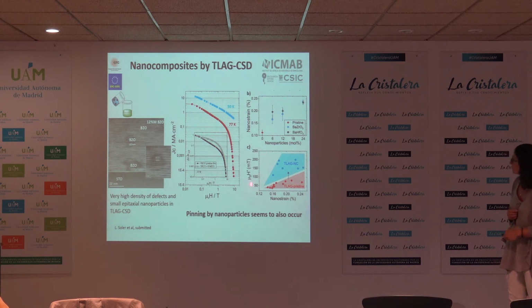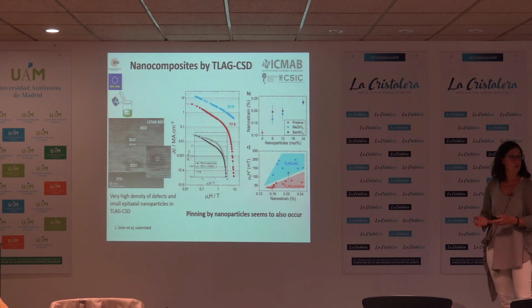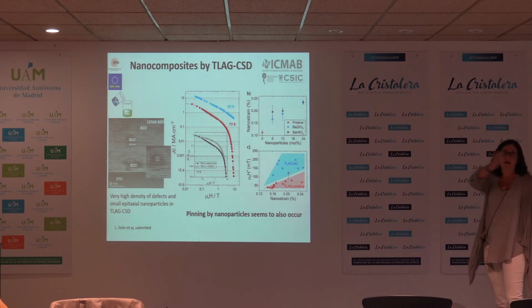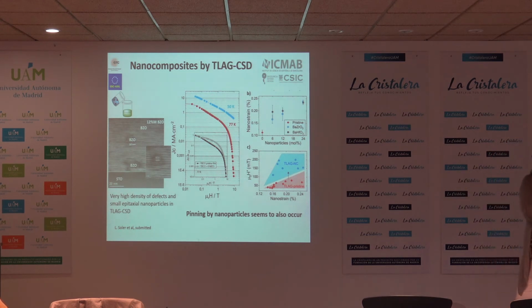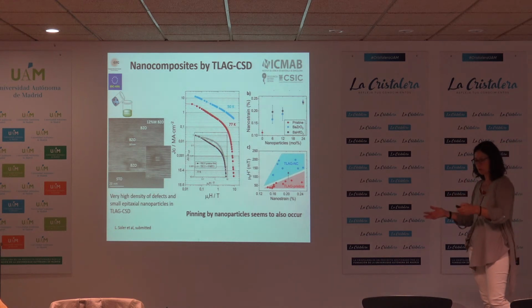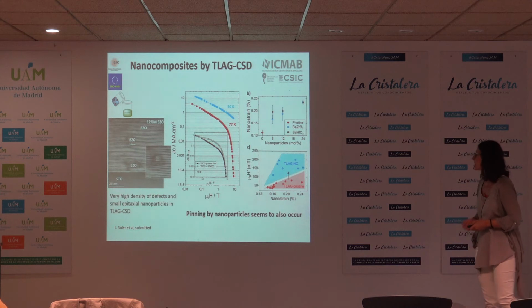And we also have been able to see that the H star depends on the nanostrain, but also for the same nanostrain, we do have higher H stars. That means that the small nanoparticles are also contributing to this process, so that we can really get all the knowledge and all the benefits that we had for the standard CSD process in this very fast, ultra-high transient liquid assisted growth.